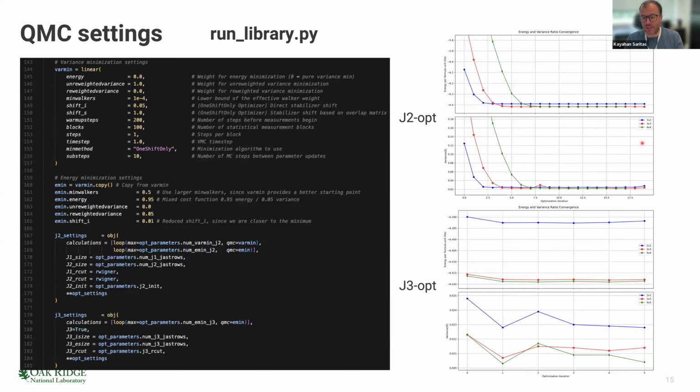see when you do the energy extrapolations, whether they deviate from a linear line that you want to extrapolate over those points. And with the J3 optimizations, I have a smaller number of steps in here. This is indicating that the scale is also much smaller here compared to the J2 optimization, because we are already using the optimized J2 parameters in the initial set of runs in here. So this also highlights the difference between the 2x2 and the 3x3 and 4x4 cells.